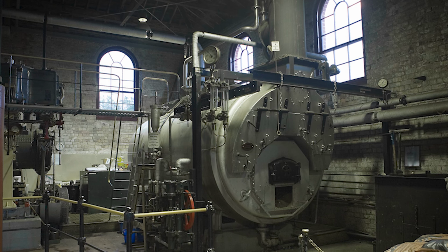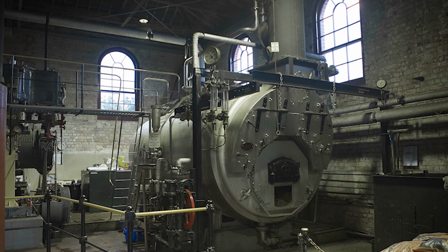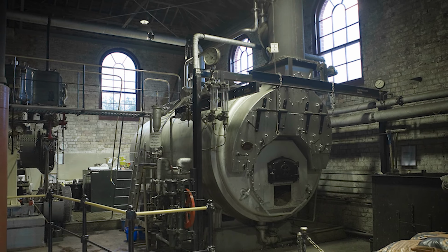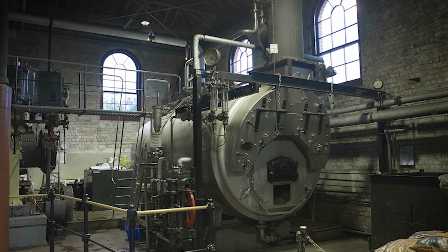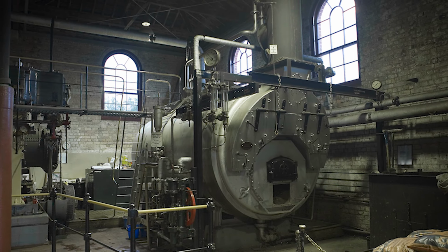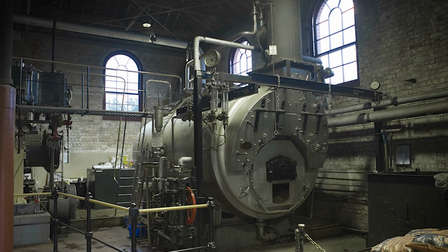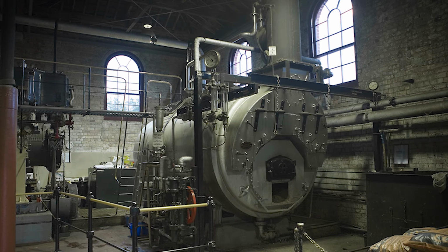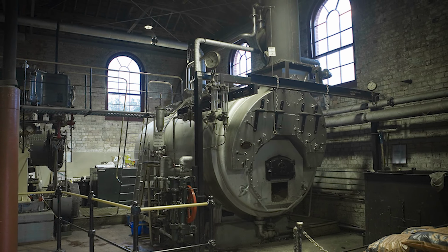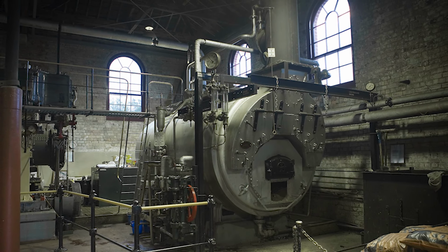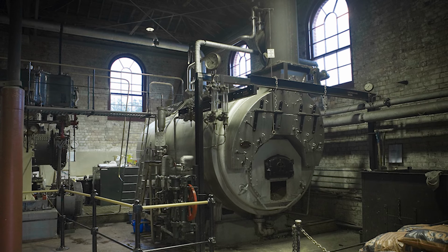5 years into operation, the first comprehensive inspection revealed results that surprised even Carson. Using the same measurement techniques that O'Neill had employed during construction, inspectors found that the boiler shells retained an average wall thickness of 9/10 of an inch, a loss of only 1/10 of an inch from the original 1-inch specification.